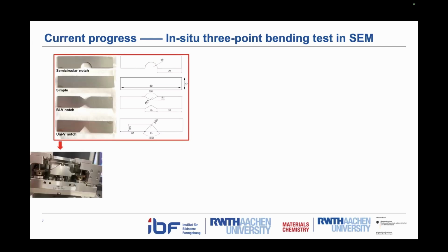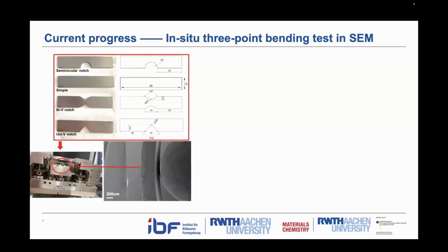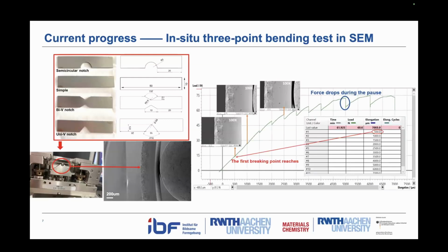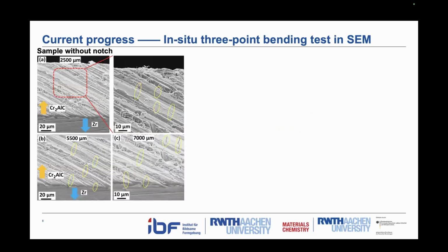Then we put the coated samples into a bending module and inserted the whole bending module into the chamber of the SEM. Then we carried out interrupted in situ 3-point bending tests to record how our samples were deformed during the test to identify the failure mechanism. Based on the SEM images we have recorded, for example here, we use a sample without any notch for explanation. When the displacement of the loading rod reaches 2,500 micrometer, cracks appear in the coating, which means the coating has fractured and failed already.